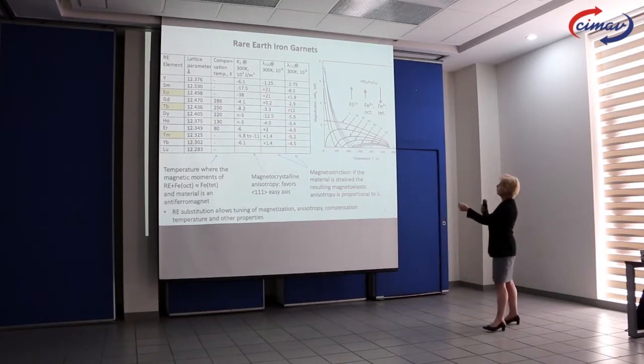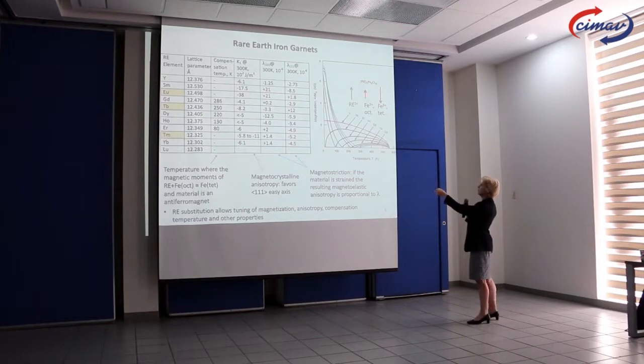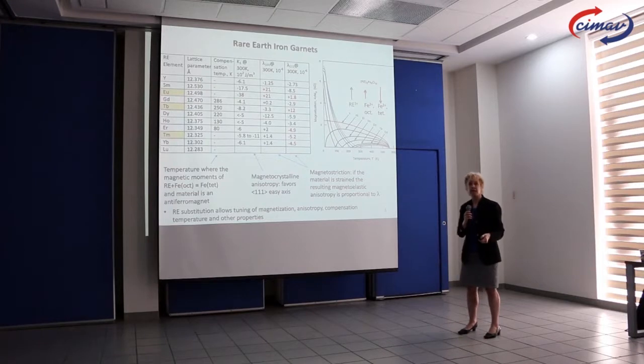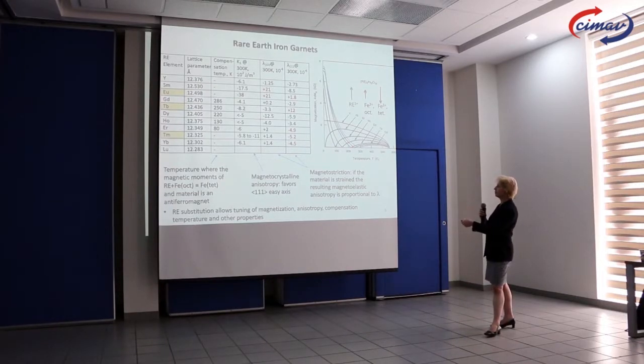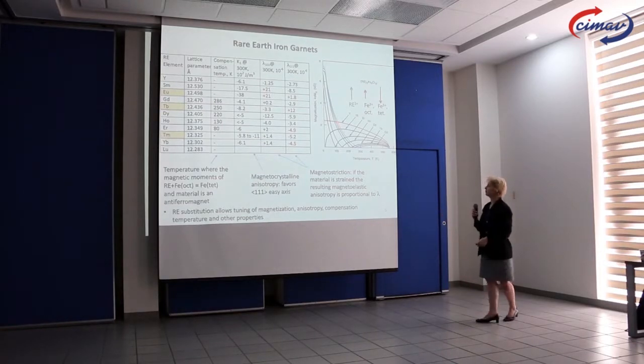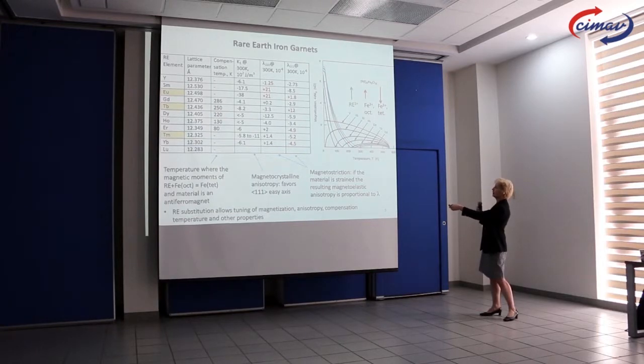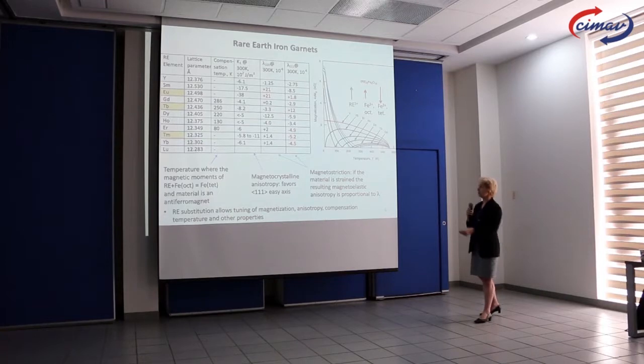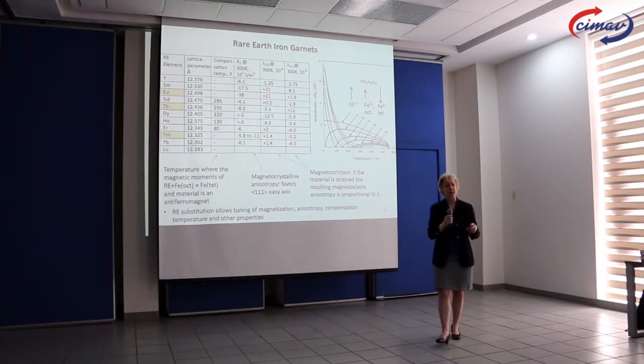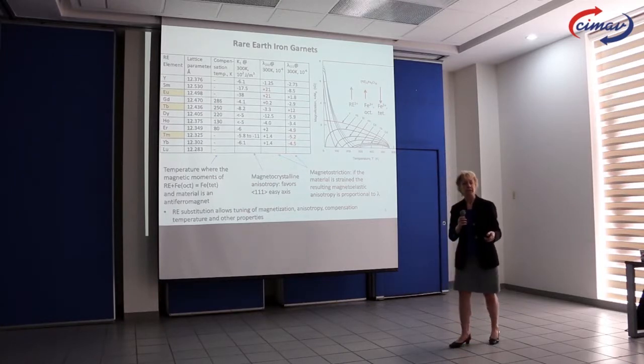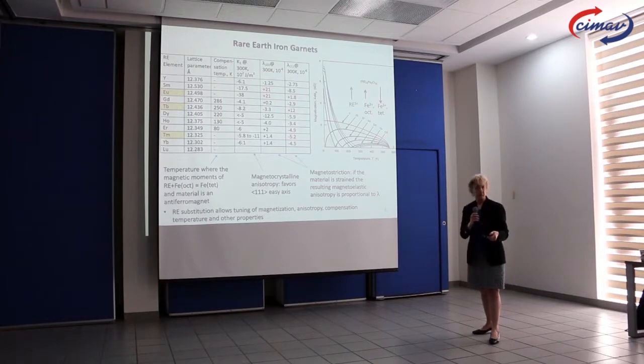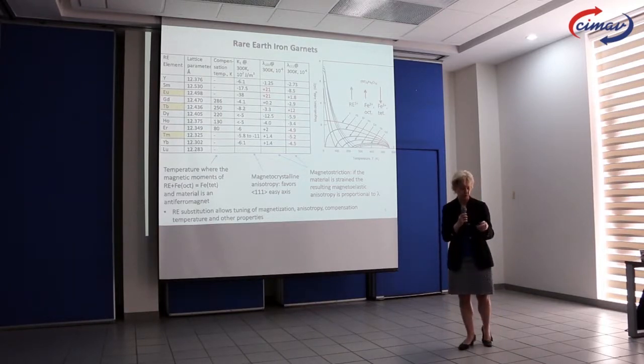And what that means is that if you look at this magnetic structure, we have iron 3+ in the tetrahedral sites pointing one way and the other two pointing the other way. When the sum of those is equal to that, the material is actually antiferromagnetic, and that happens at a compensation temperature which is different for each of these garnets. So if we plot their magnetization as a function of temperature, some of them go to 0 and then come back again, and that's the compensation temperature. And some of them just change smoothly with temperature. Those ones do not have compensation, and that's an example of YIG, where there's nothing here, so we can't have compensation. So, in summary, by changing the rare earth ion, we can tune a lot of the properties of these materials. And I'll show you later, we can also tune optical properties, which is not on this chart, but we can tune the way they interact with light.